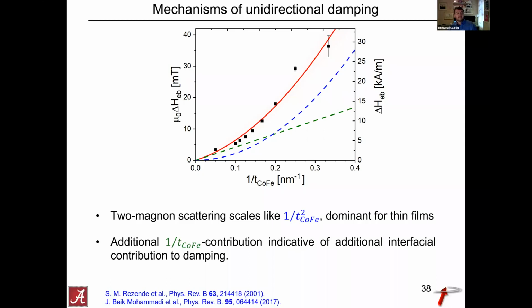But you can see that there is such a contribution, but on top of that, you have to add a linear contribution, so 1 over the film thickness, to actually describe this data. So what we think is happening here, while two-magnon scattering is definitely a significant contribution to the line widths in those films, there is another term that scales like the inverse film thickness that also contributes to the damping in those films. And this is not the only system we found this kind of behavior in.